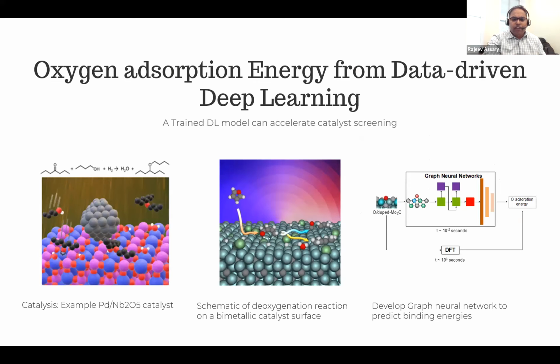Just for example, if you look at the middle figure here, if you look at benzene or any other organic molecule with oxygen on it, and you attach it to the surface, the oxygen gets trapped into this top surface, and it causes the phase transformation of the surface. So if you can remove oxygen very efficiently by adding hydrogen, it will come off as water. Then the catalyst surface could get regenerated.